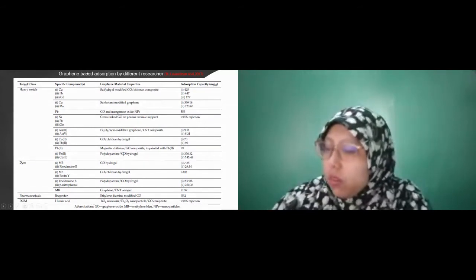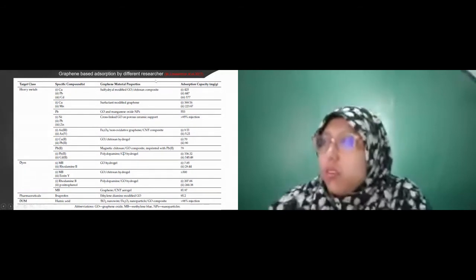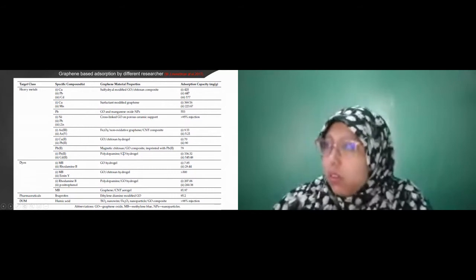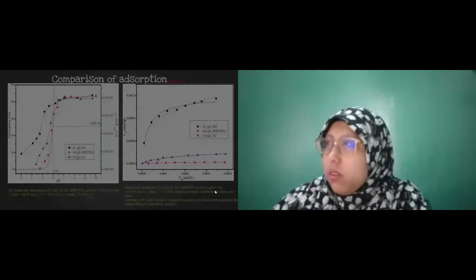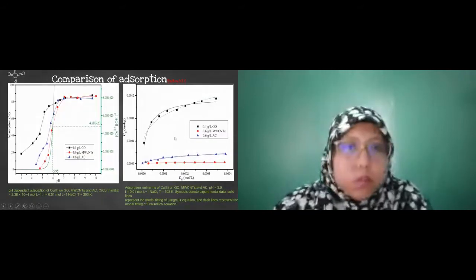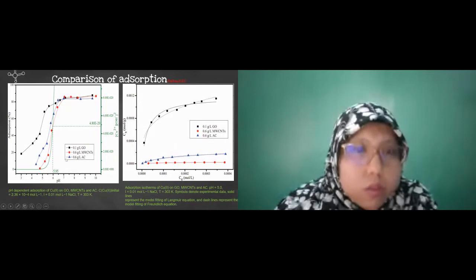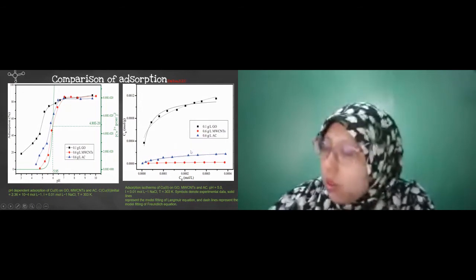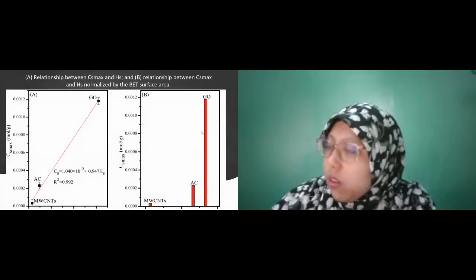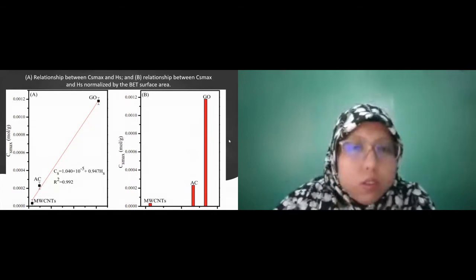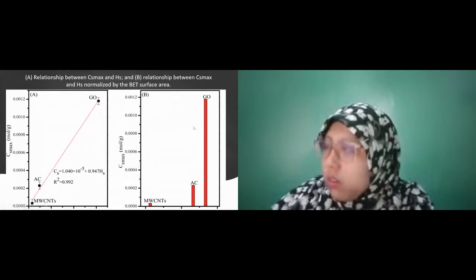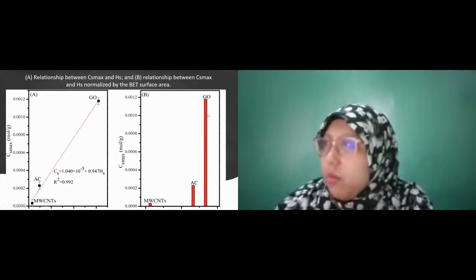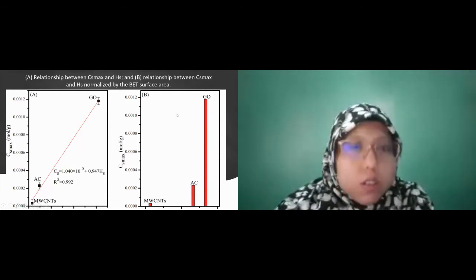Now, here also, from the literature we have found graphene-based adsorption. Different heavy metals are adsorbed by graphene very efficiently. So if we compare the adsorption of heavy metals by graphene oxide, CNT, and activated carbon, as you see, the adsorption by graphene oxide is higher. And here also we can see that the activated carbon BET surface area and graphene oxide BET surface area have a very big difference.